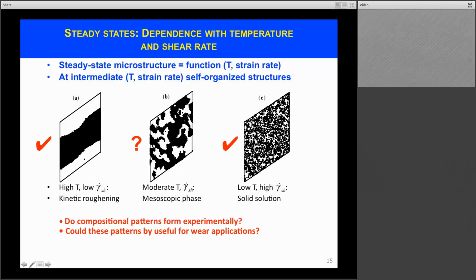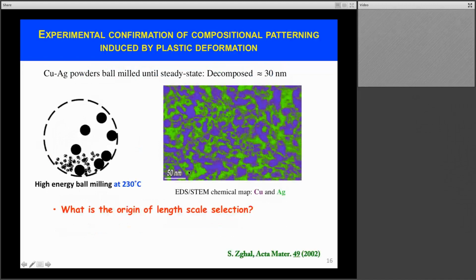So what we did naturally is to ball mill copper silver at intermediate temperatures and look at this by TEM. On the left-hand side, you have a schematic drawing of these powders being ball milled. Here, the milling took place at about 230 degrees Celsius, which is the temperature where thermal diffusion in copper silver becomes significant. And on the right-hand side, you have a chemical map obtained from scanning transmission electron microscopy, where copper-rich regions show up as purple or blue, and silver-rich regions as green. And you can see that indeed here we have a nanocomposite that is very similar to the one we observed in the atomistic simulations I showed you in a couple of previous slides. So it seems that the self-organization reactions do take place experimentally.